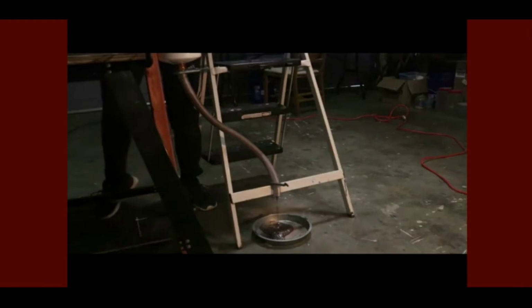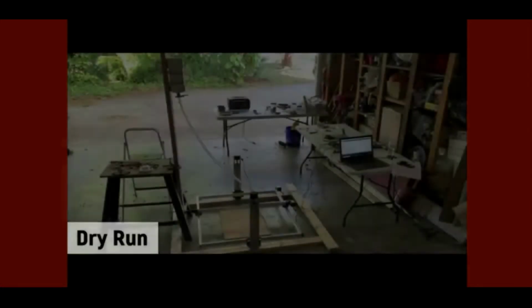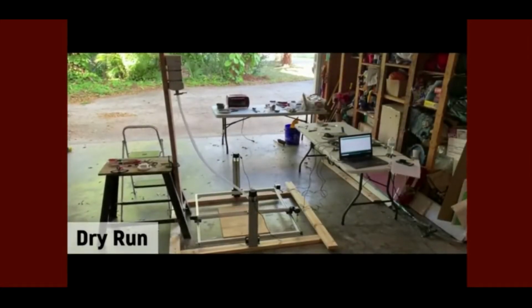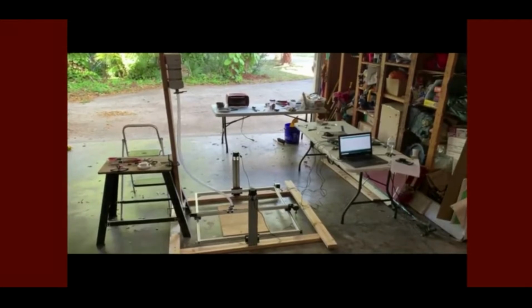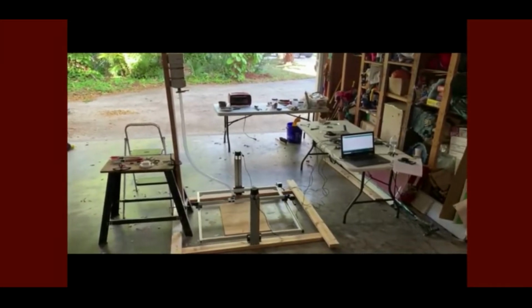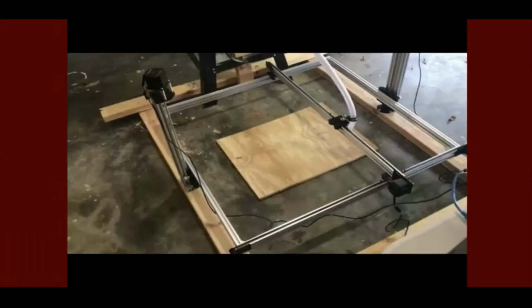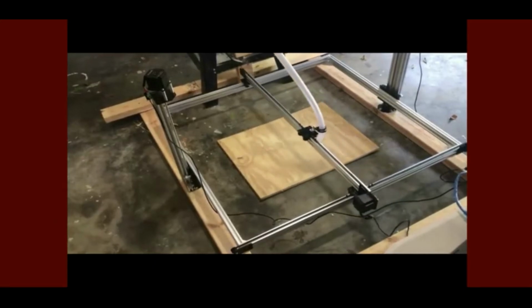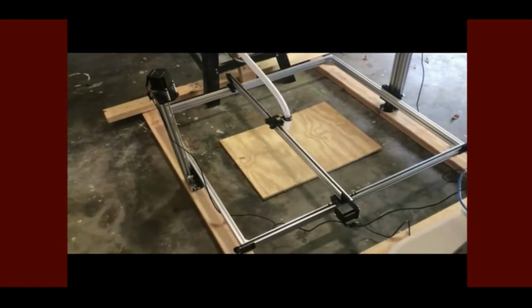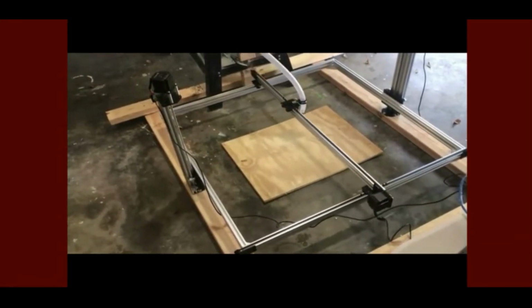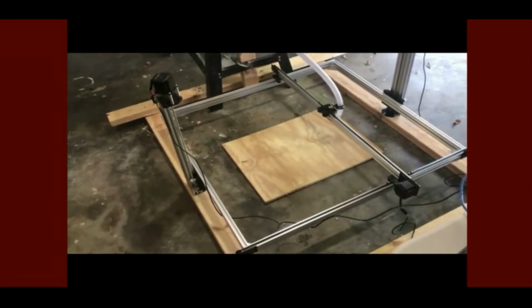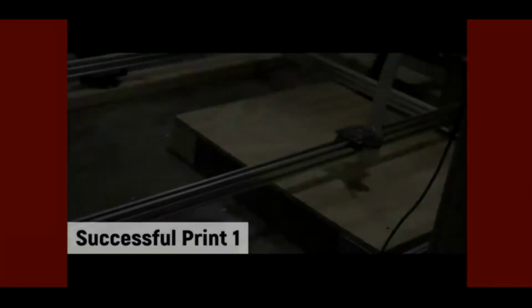And as you can see, it's coming out in a pan here, and I weighed the mass of that pan before and after to calculate efficiency. So this is the integrated system, which is basically just combining the extrusion system and the gantry system, which I had already created. And here you can see that I programmed the nozzle to move around in a 20 by 20 centimeter square. And after each tracing of the square, it moves up just half a centimeter.